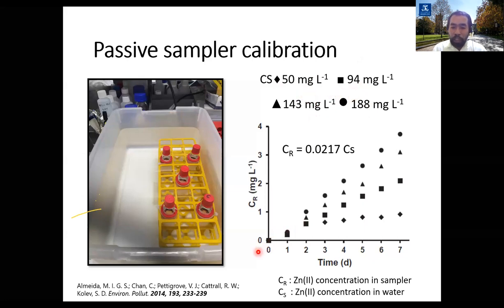We monitor the concentration of zinc accumulated within the receiving phase of each passive sampling device. As you can see, with increasing concentration of zinc in the source solution, we have increasing accumulation of zinc in the receiving phase. From here, we can build the correlation between the concentration of zinc accumulated in the receiving phase and that present in our water system. And this will be used for interpreting our results from field experiments.